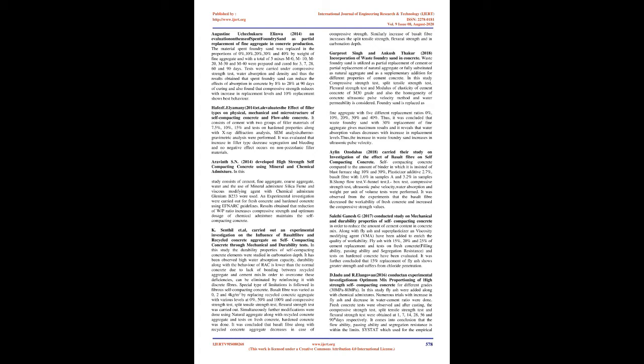D. Literature review. T. Parthiban, 2017, investigated the durability of concrete by adding basalt fiber which does not contain any other additives. In this study, trial tests for the concrete with cement, fine aggregate, coarse aggregate, and basalt fiber with 0%, 1%, 2% were conducted to prove the difference in durability parameters. Rapid chloride penetration test, water permeability test, and sorptivity test were conducted for the concrete mix. In this experimental investigation it was concluded that fiber arrests the formation of micro cracks, and thus in RCPT, WPT, ST the optimum value was attained at 1% of fiber replacement. The test results found that 1% replacement holds good for durability parameters.